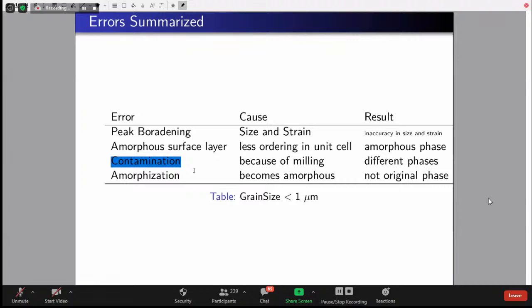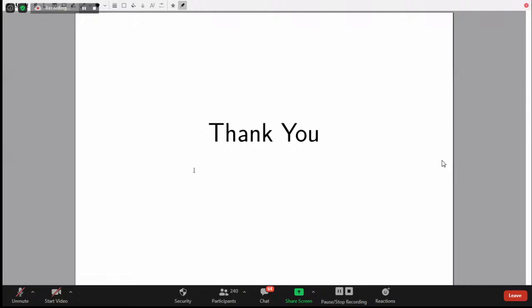Other one is amorphization, which is not actually in our sample, but when we grind it more and more, we will make it amorphous. It will lose its three-dimensional ordering. The long range ordering will be absent, and it becomes amorphous. All these are made by the user, which is not actually in the sample. So all this care we should take before we go for the diffraction experiment. I believe with this I will stop boring you.